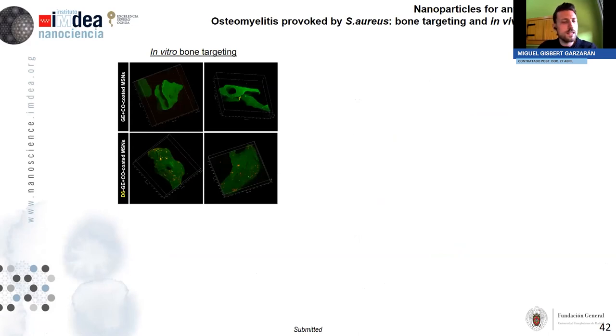Okay, so I will finish very briefly by showing some pictures of the bone targeting capability of the nanoparticles. So first, we carried out again the in vitro experiment with the trabecular bone. And as we can see, D6 stands for the hexapeptide of polyaspartic acid. Only in the case where we had this bone targeting moiety, we could observe the presence of nanoparticle aggregates around the bone. However, when we just had the nanoparticles without the bone targeting, we didn't observe anything.